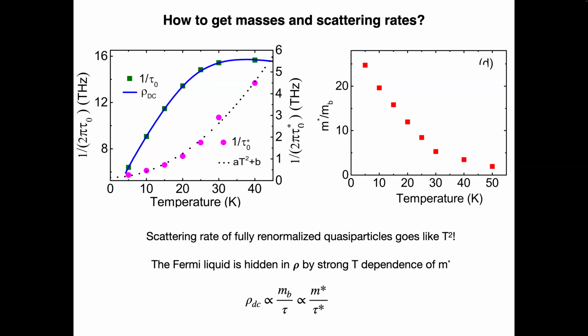So what comes out of this is the idea that, and it's kind of obvious in retrospect, in a heavy fermion system the masses are strongly renormalized as a function of temperature. In this case here, the mass is kind of doing this. I wouldn't say it goes like 1 over temperature, but it's roughly 1 over temperature. So you have a scattering rate which goes like T squared and a mass which goes like 1 over temperature. And this is the key. I don't think there's any debate to this. This is why the resistivity goes linear in T in cerium cobalt indium 5.